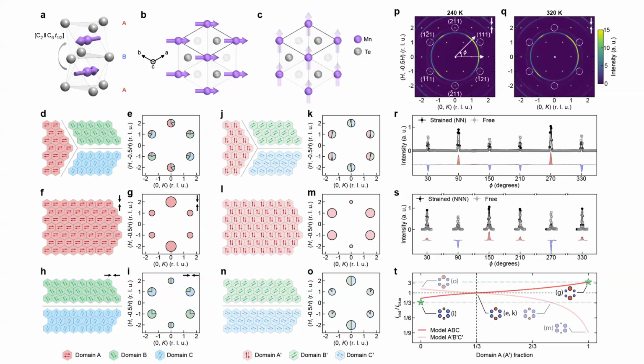Thank you, Pengcheng, for the very nice talk. I just wonder, this manganese telluride has this intrinsic magnetostriction property, where you cool down and it has its own strain. When you apply the external strain with the device, I'm wondering if you have to make any consideration for the intrinsic magnetostriction. Oh no. Like I said, the magnetoelastic effect in the case of manganese telluride is exceedingly small. When you put strain on, you don't change the magnetization much at all.